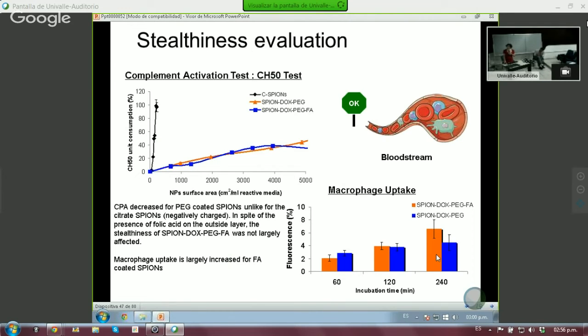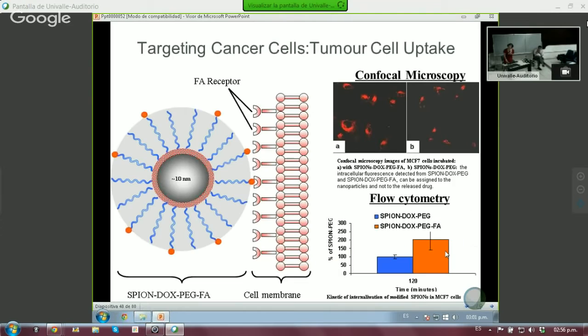And if we wait much longer, 240 minutes, you can see that the folic acid had some influence and improvement over the SPION with PEG without the folic acid. And here we looked at the tumor cell uptake, and this is again the diagram of what we have synthesized. So we have our 10 nanometer iron oxide SPIONs, and we have the DOX around it. And then we have the polymer and the folic acid. And this is the cell membrane.